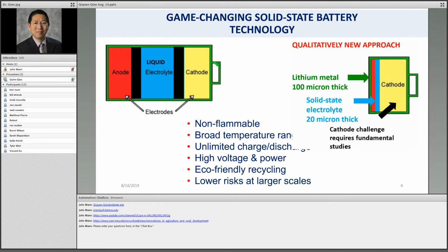So all solid state, you can also make this. If you look at this diagram here, this is all solid state, and at this moment the highest capacity batteries will be based on lithium metal. With lithium metal, if you use liquid electrolyte, that can easily cause dendrite growth because the lithium surface is very reactive. The solid state electrolyte can function as a surface modifier or surface passivation layer that prevents lithium dendrite growth.